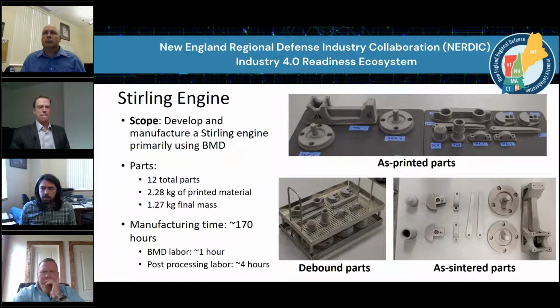And then the final mass of those parts is the part mass once the process is finished. They're in the as-sintered state, so the binder material has been removed, and the interface materials are also removed from that. So to create these parts, the manufacturing time, that's the amount of time for the printer, the debinder, and the furnace to run and produce these parts, was approximately 170 hours. But the actual labor on the operator side, that operator was myself, was approximately 1 hour.